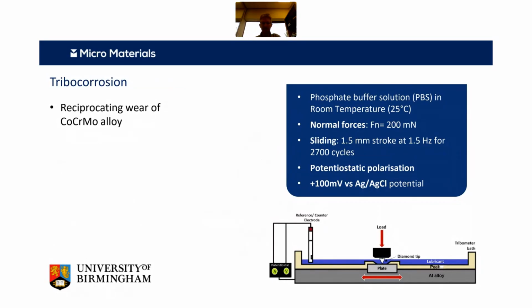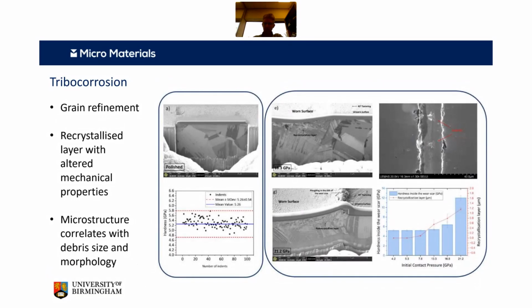So here's a simple example from the University of Birmingham now. Here they are looking at cobalt chrome alloy, and they're looking at reciprocating wear of this in a phosphate buffer solution, sliding over 1.5 millimeters, and then essentially seeing what happens. This is Mike Bryant's group at the University of Birmingham. So first of all, you can see on the unmodified surface here, you can mechanically map that unmodified surface, and you can see it has a fairly tight hardness distribution. So it's very hard for a biomaterial alloy, cobalt chrome. These are fairly typical values, just over 5 GPa.